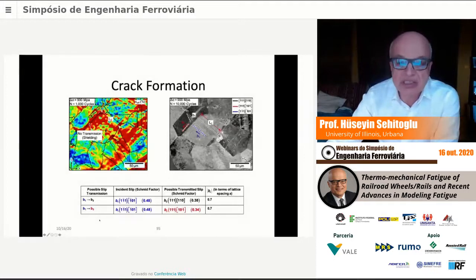And we see examples of this, the cracking phenomena associated with special kinds of boundaries, special boundaries where there are finite residual stresses. These are the residual Burgers vectors, and these are the residual Burgers vectors that are calculated at these boundaries. And when they're large, one can get conditions conducive to cracking.